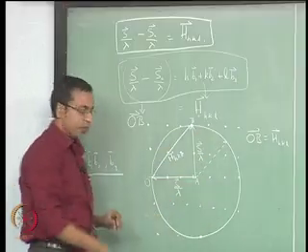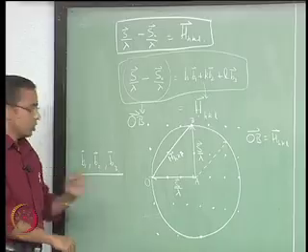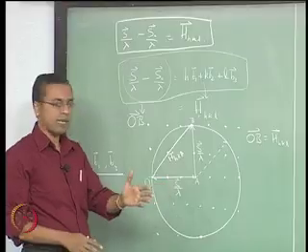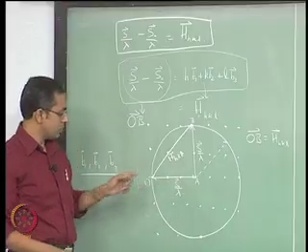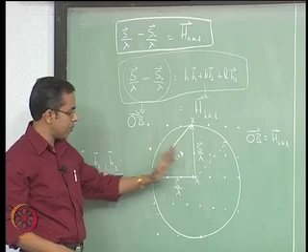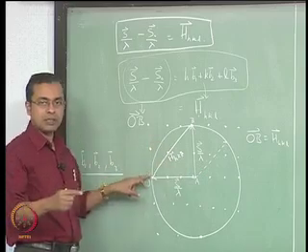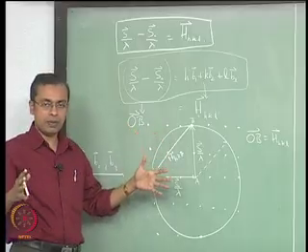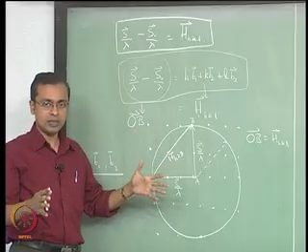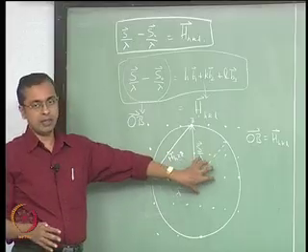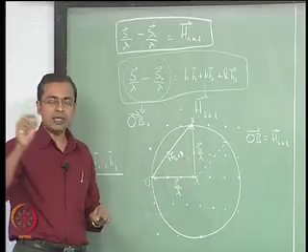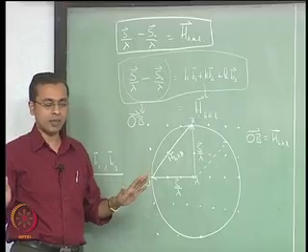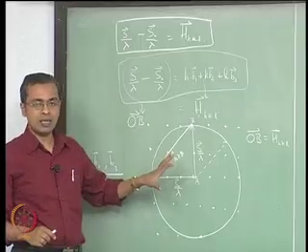So what you see as a circle in 2 dimensions is actually a sphere, and what I have just shown you is a 2 dimensional set of points because I only used B1 and B2. The reciprocal lattice itself will exist in 3 dimensions for a real material, because you will have B3 also. In the same way that I plotted B1, B2, you can additionally put B3 points here and behind the board. So you will get a 3 dimensional set of points corresponding to valid reciprocal lattice points, and you will have a 3 dimensional sphere. Any place the surface of the sphere touches one of those reciprocal points, you have a valid condition for diffraction.